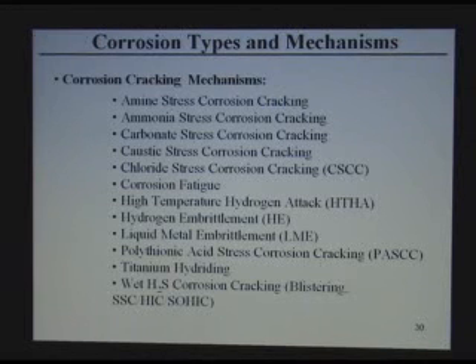Carbonate cracking is also there, where we have a high carbonate content at high temperatures and high pH. The carbonate ion can cause stress corrosion cracking. Caustic can also cause stress corrosion cracking for carbon steel if it is not stress relieved. Chloride cracking, of course, with stainless steel, which I showed you. I'll show you some figures. Corrosion fatigue: if you have a fatigue environment and a corrosive environment, it causes corrosion fatigue. High temperature hydrogen attack, which you have seen a few minutes ago.